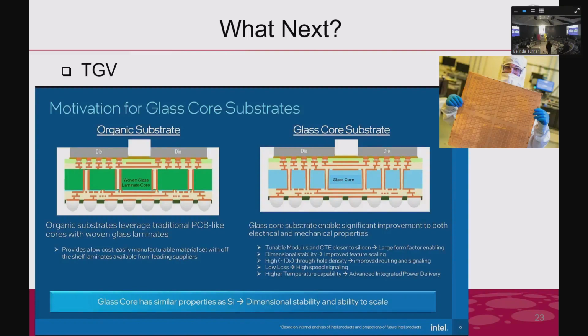About this last slide, as you mentioned, Intel is thinking to replace silicon with glass. It's already going on. It's not thinking. Yes. One of the reasons silicon is there is because of its semiconductor property. Yes, because once you heat up, the loss will increase. So how can conductivity be introduced in the glass? Oh, it's the same. Remember we said they have to fill the copper. They fill the copper into the channel, the hole. So they use the same process. The difference is they change the silicon to glass. So that's what they are currently doing in their packaging.